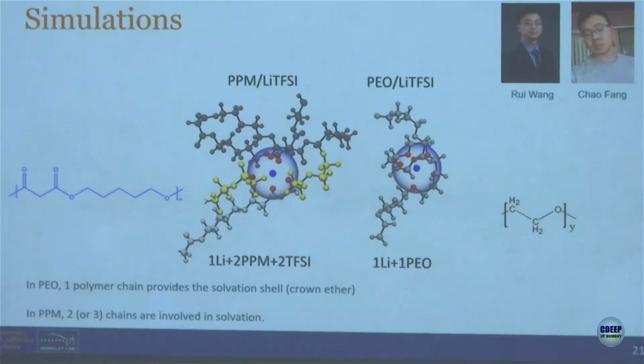It has the exact spacing of a crown ether, which is known to solubilize cations, like lithium. What was news is that when you look at this polypentyl malonate, only these carbonyl oxygens interact with lithium. That turns out from simulation. And you need at least 2 chains to be interacting with this lithium. So in PEO, you have 1 chain. In PPM, you have 2 or 3.